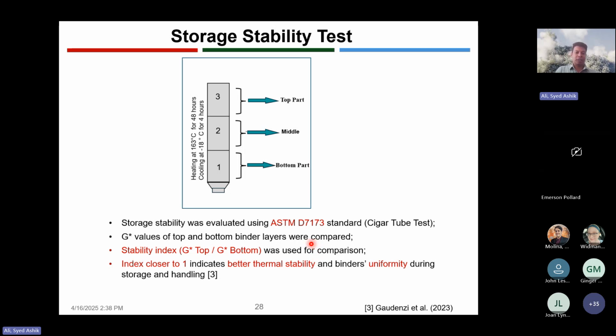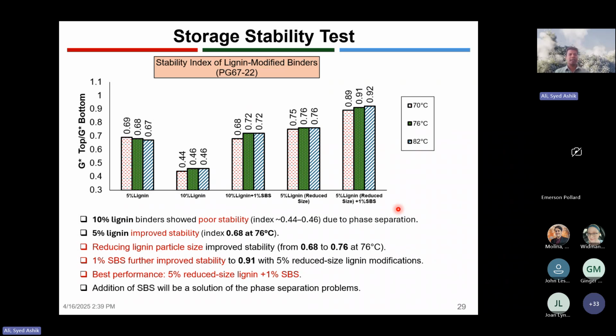An index value of 1 will indicate good thermal stability or storage stability of the material, and also that there is better uniform mixing of the lignin into the binder. So this graph here shows the stability index of lignin modified binder. When we added 10% lignin, the ratio of G star of the top and bottom sample went down very low. We found on average a stability index of 0.46, which indicates very poor stability. That means with the addition of 10% lignin, we can expect phase separation, and it will be difficult to get a uniform lignin modified binder.